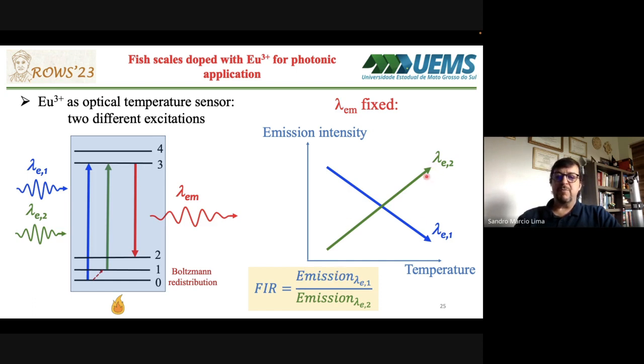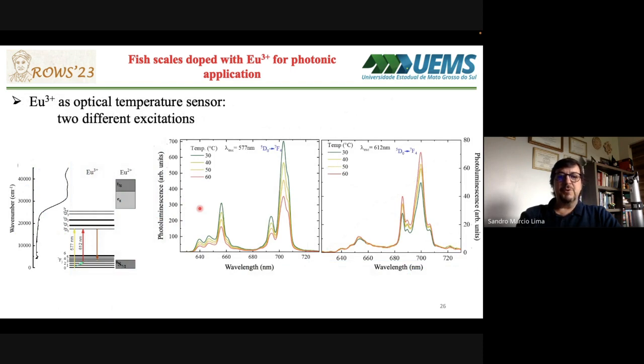So by performing this ratio and correlating with the temperature, we can use this sensor to indicate the temperature of the probe ambient. So in the following, I will show the results that we obtained with hydroxyapatite doped with europium 3+. So we performed the experiments with the excitation of europium 3+, but we know that we also observed the europium 2+ in our samples.